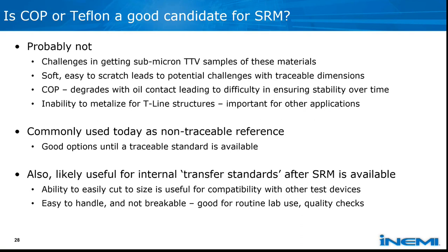They are commonly used today as non-traceable references, and they're good options until a traceable standard is available. In the future, we see these materials being really helpful as transfer standards after a standard reference material is available, because you'll be able to take a calibrated instrument, calibrated using the standard reference material, and then measure an individual sample of these materials as transfer standards. Because they're easily cut to size, it makes them easily usable in other test devices, enabling development of new devices with some connection to a traceable standard. They're also easy to handle and generally not breakable, so they're good for routine lab use and quality checks.